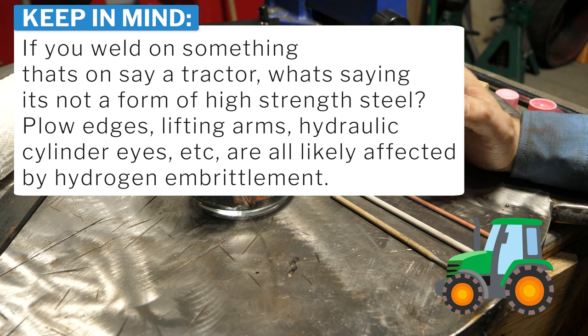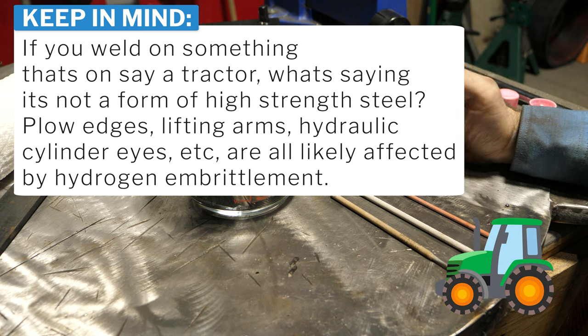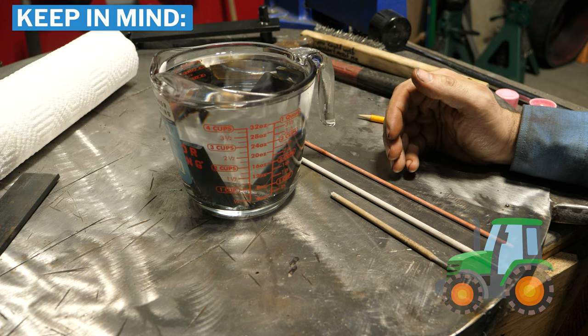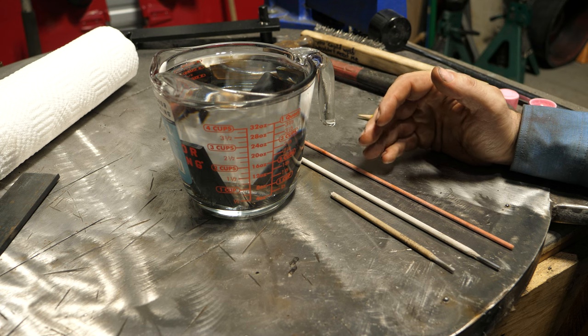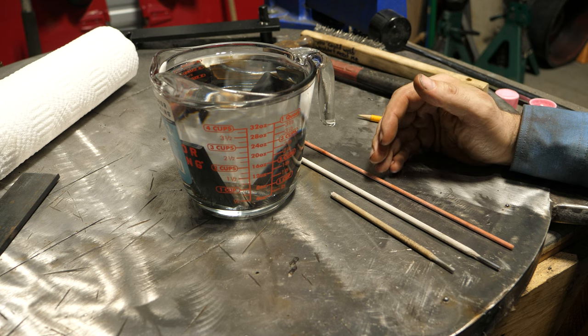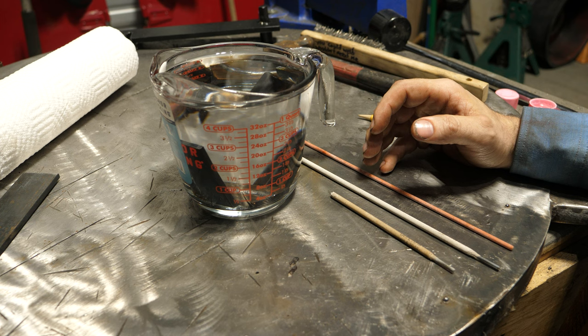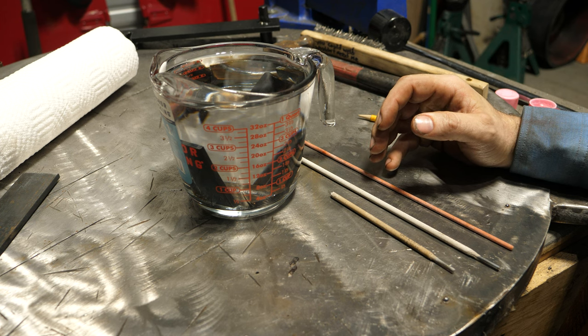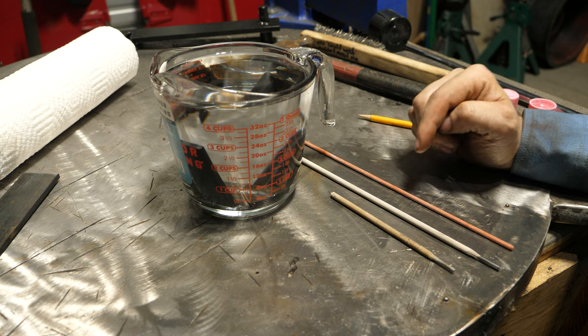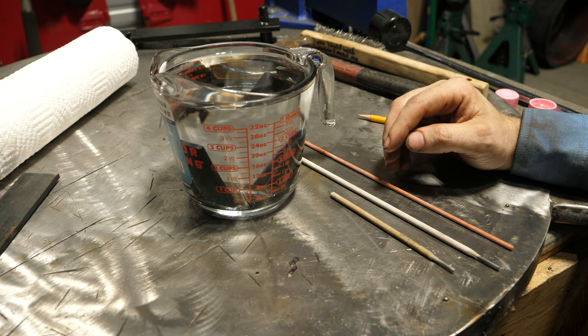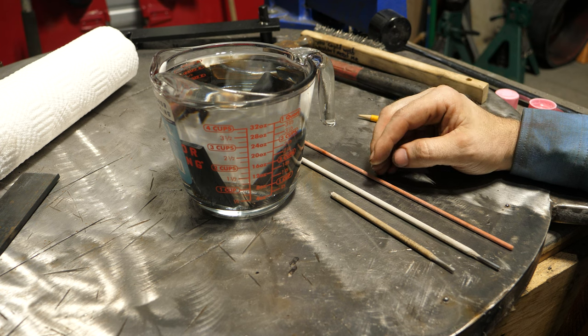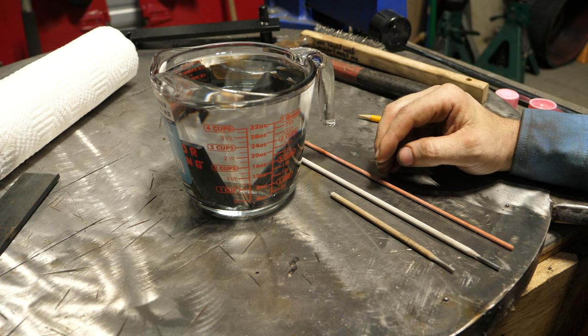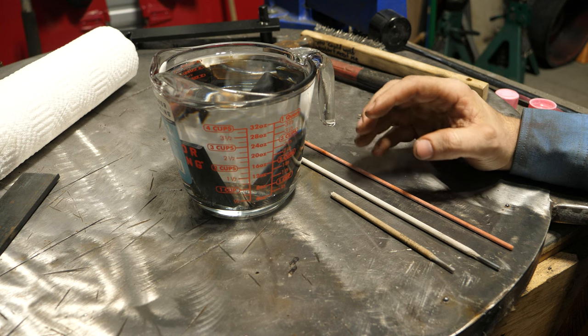Now I didn't cover it earlier, but I'll mention it now. When you get into welding big structural components—and it's more common, I guess, on high-strength pipe—it's very common to use blow torches or burners to preheat the steel. So that as you weld it, that steel is hot, because if you keep the steel or whatever material you're welding at an elevated temperature, it will boil off the hydrogen before it ever has an issue or a risk of getting absorbed into that molten metal weld pool and in the heat affected zone and cause brittle failures.